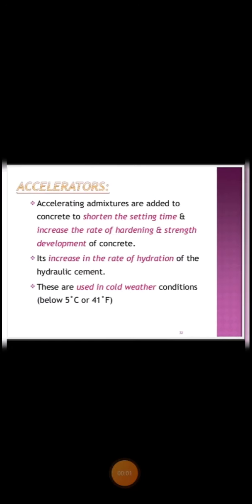The third topic is accelerator. Accelerators are admixtures that cause an increase in the rate of hydration of hydraulic cement. These are added to concrete either to increase the rate of early strength development or shorten the time of setting, or maybe for both purposes. These are used in cold weather conditions, which is below 5 degrees Celsius or 41 Fahrenheit.